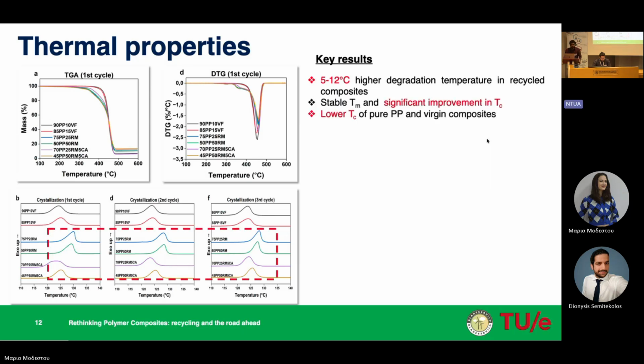And also, we got to know that the melting temperature of these composites was quite stable even at higher temperature ranges. We were also able to see a significant improvement in the crystallization temperature. The crystallization temperature for recycled composites was quite good compared to the lower crystallization temperature we usually see in pure polypropylene and virgin composites.